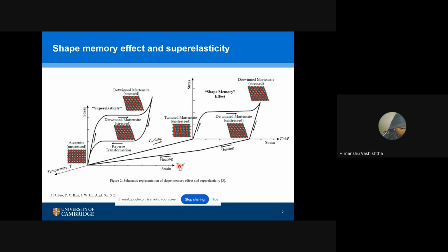So when my temperature is greater than the austenite phase - meaning when my austenite phase has been stabilized at, let's say, some temperature X, and my temperature is higher than that X temperature, in that condition, if I'm applying any stress, my austenite phase is stable, so the deformation has started from the austenite phase. If I'm deforming it, I'm forming martensite, and when I'm unloading it, it will return to the original position.